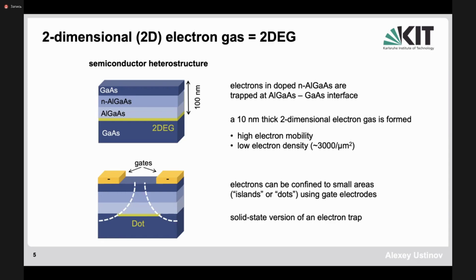And the motion of electrons occurs in only a 10 nanometer thick layer of electron gas, which is so thin that the electron states are quantized in the direction perpendicular to the substrate, in the vertical direction on this plot. And the reason why it's possible is that the electron density in this electron gas is very low. And for low electron density, you can recall your knowledge of the Fermi gas. You would have relatively low mass and relatively large Fermi wavelengths. So the wavelength of electrons in these two-dimensional structures is typically 2 orders of magnitude larger than the Fermi wavelength of electrons in a metal.